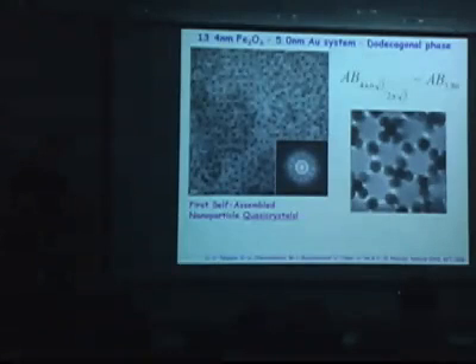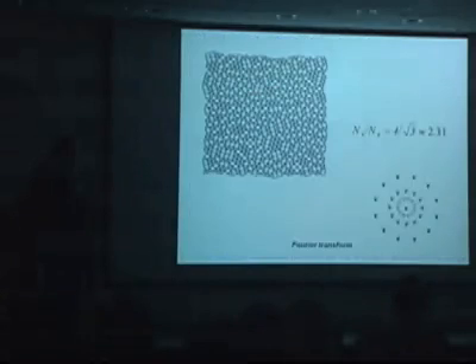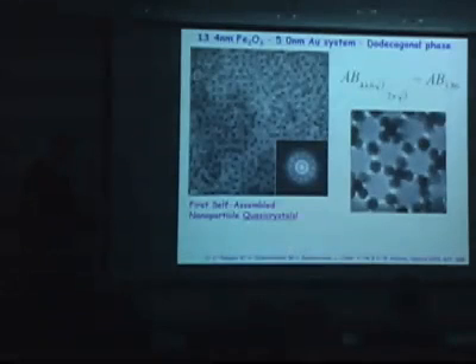Once we cancelled out, or minimized, the internal energy contribution and cancelled out translational and rotational entropy contributions, then the configurational entropy of the lattice itself can play an important role. And in this structure, since it's the highest-entropy possible packing, the configurational entropy will be higher than any periodic lattice. Okay, that was a first demonstration of nanoparticle quasicrystals.